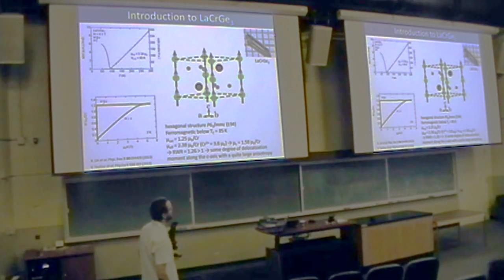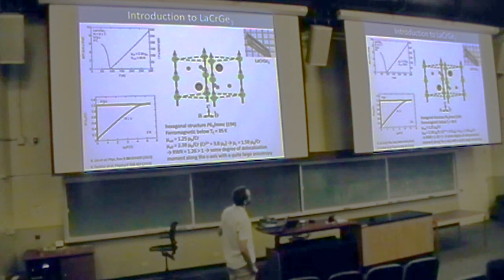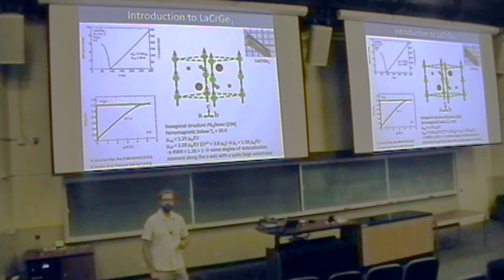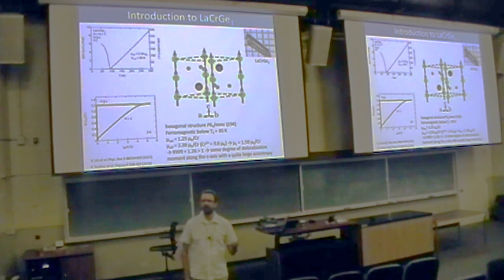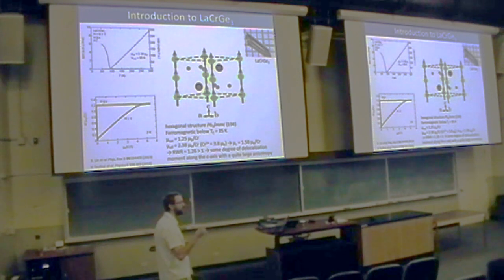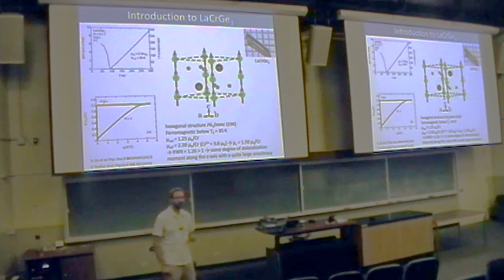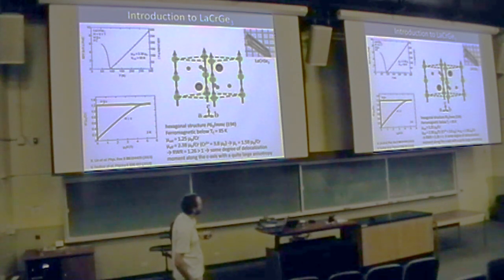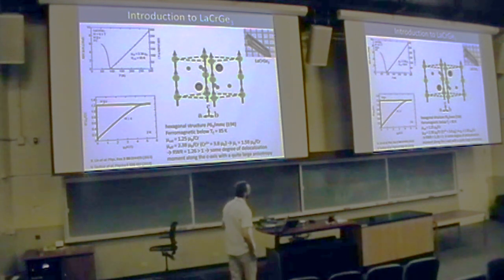This is a compound that has a hexagonal crystal structure, and it becomes ferromagnetic below a Curie temperature of 85 Kelvin. And then it has an effective moment that is somewhat smaller than what you would expect for chromium 3+, and so that tells us that there is some degree of delocalization of the magnetism in this system. And also the saturation moment is 1.2 µB per chromium, and there is quite a large anisotropy in the system. The moments are aligned along the c-axis, and you have a quite large magnetic anisotropy.